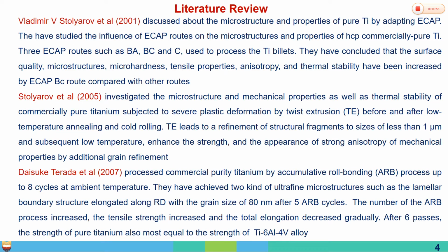We conducted a literature review related to this work. Different researchers and academicians have worked with different severe plastic deformation techniques in order to increase the strength of commercial pure titanium. Some of these I have highlighted here. First is the ECAP route used for increasing the strength of commercial pure titanium. They achieved good strength and tensile properties by using the ECAP BC route compared to the other routes.